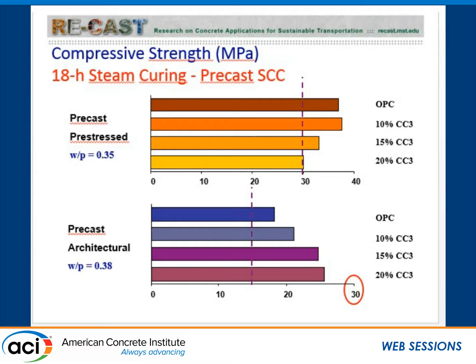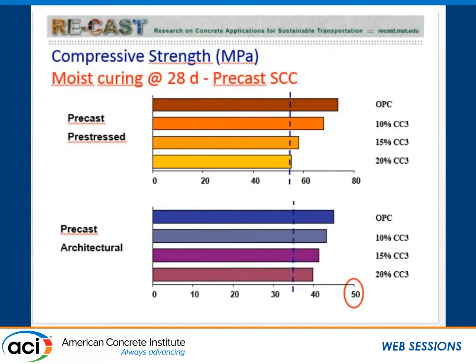And for the type 1 cement, it seems like you are promoting strength gain because of nucleation when you are replacing type 1 cement with calcium carbonate. Again, the targeted strength at 18 hours of steam curing was 15 MPa, and you largely meet that requirement. And after 28 days, for the structural pre-stressed concrete, we had a 50 MPa requirement. And again, we meet it everywhere except the 20% calcium carbonate. And the 35 MPa requirement was met with all 4 concretes, with or without calcium carbonate.